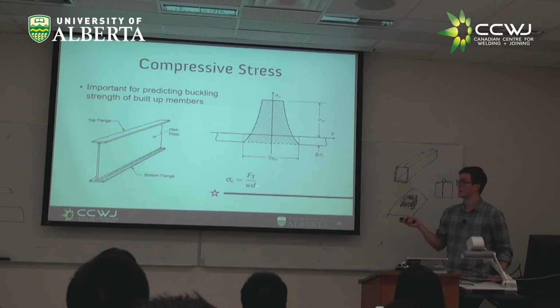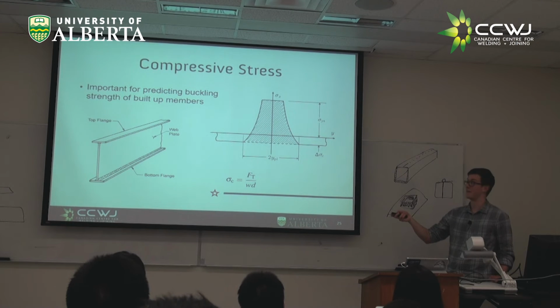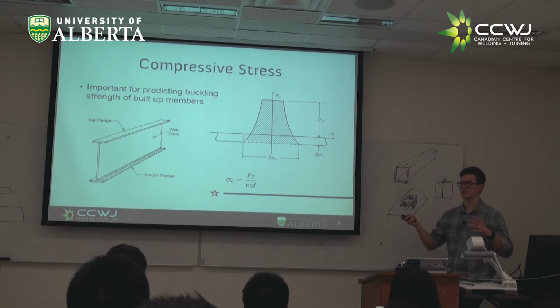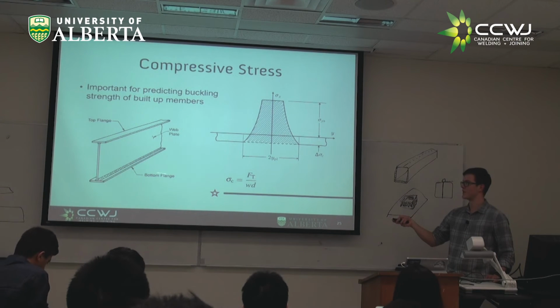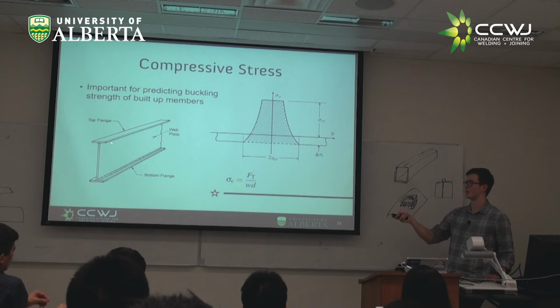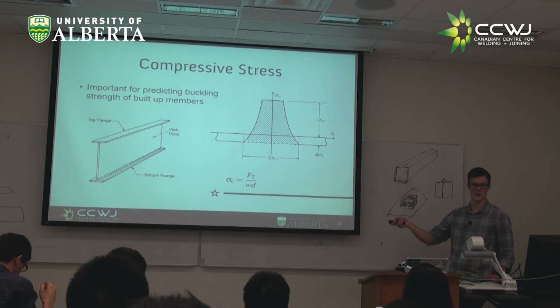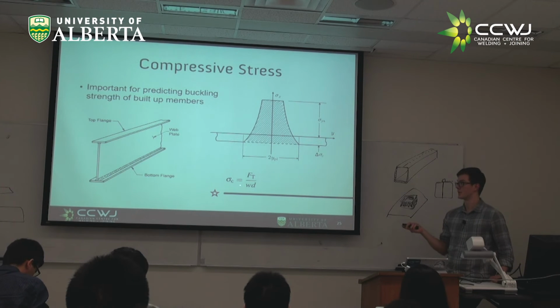I don't know if I mentioned, I think it was on the slide, but this would be called the tension force. And people were worried about what this force was because if you have that tension force here, you have compressive force in the middle of this plate, and that affects the buckling strength of this column. And a really simple approximation is just to take that total net tension force, divide by the total area, where this is not just the width of the column, but the total width, the width of this plus the width of this plus the width of this, times the thickness. And you end up with your compressive stress. And that compressive stress you use to calculate the effective reduction in buckling strength of your material.